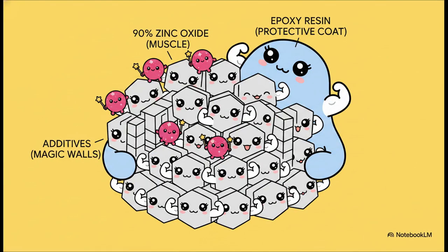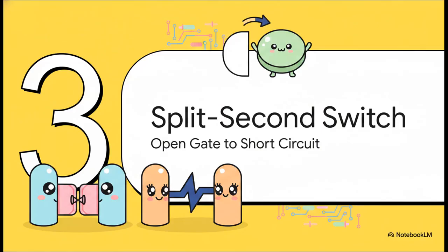The zinc oxide, which makes up about 90% of the core, that does all the heavy lifting. But it's the tiny amounts of additives, things like bismuth and cobalt, that form those magical grain boundaries that can switch from insulator to conductor. And that epoxy resin? It's not just for looks. It insulates the component and, crucially, helps dissipate the intense heat that's generated during a surge. So how does this incredible construction allow the MOV to do its job in a split second?